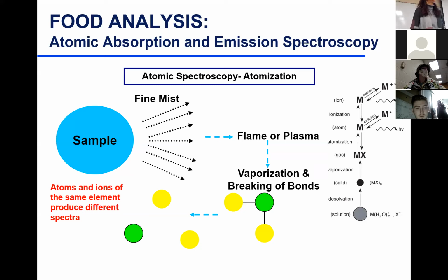This is related to the flame temperature, and that's very important. Some of you might have seen this with Cindy in the lab, where you regulate the incoming amount of air and acetylene, where you have this balanced combination to give you a flame temperature that would be sufficient to break the bonds, yet not to cause ion formation. At higher flame temperature, your atoms may ionize. And when they ionize, they absorb at a different spectra. They have different spectra. So you might get underestimation of your mineral content.